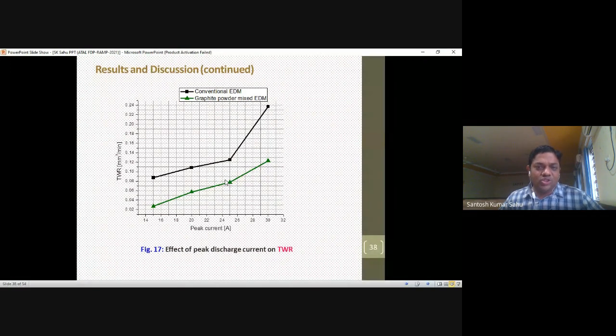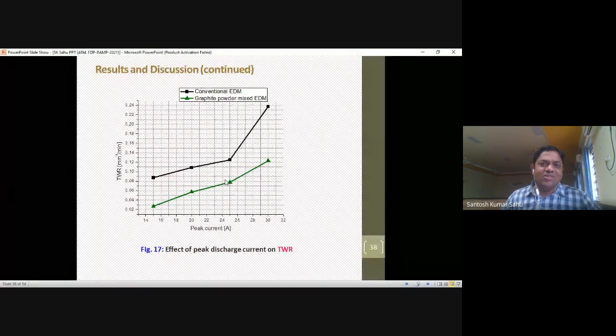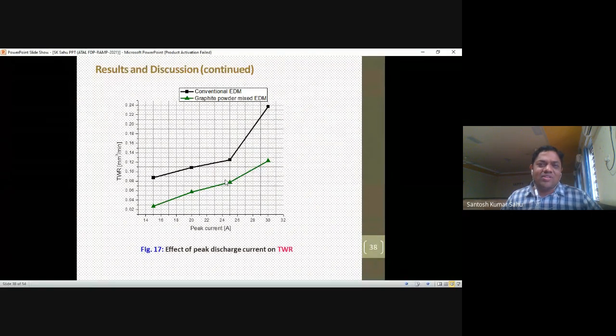TWR with respect to our current. If the intensity of current, the intensity of power, increases, then not only does the MRR from the workpiece increase, but we also lose the life of our tool. In the green mark is the graphite powder mix EDM, and the black line is your conventional EDM. We can see that the tool wear is less when adding graphite powder in the powder mix EDM as compared to our conventional EDM.